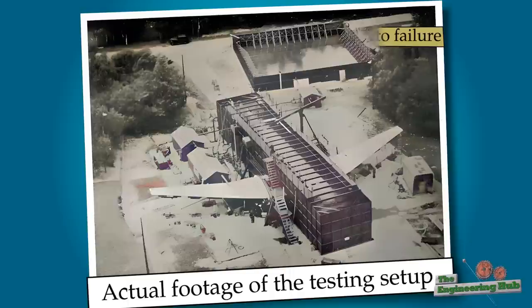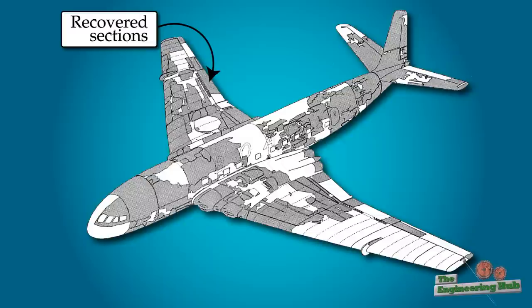After 3,057 cycles of Yoke-Uncle, a fatigue crack grew to failure originating from a rivet hole. In the meanwhile, an effort was made to recover some of the wreckage from the second crash. Signs of fatigue were identified near one of the corners of the ADF windows.